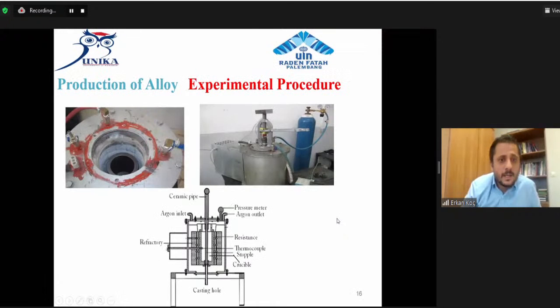For our production of alloy, the experimental procedure, our furnace, you see here, graphite crucible. In order to produce these alloys, an electric furnace which has completely controlled atmosphere. As I said before, magnesium alloys oxidize easily, so you have to use a controlled atmosphere furnace, okay?